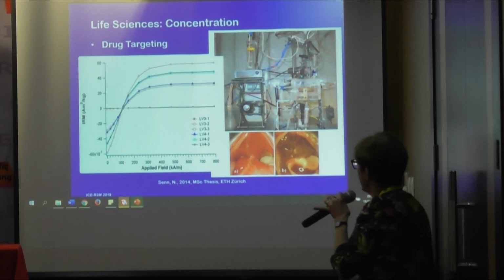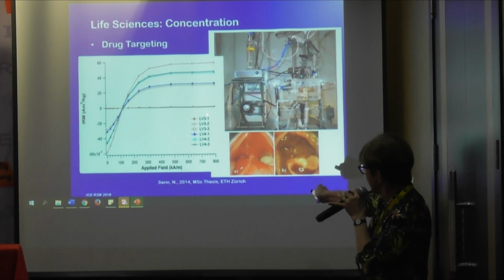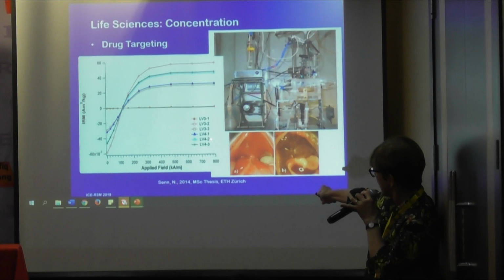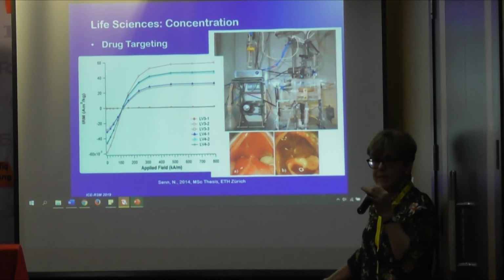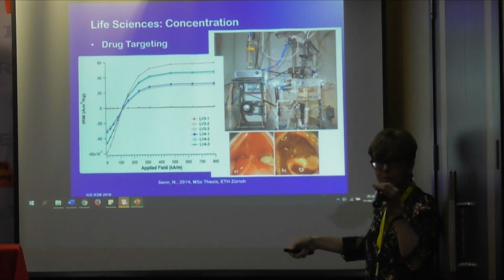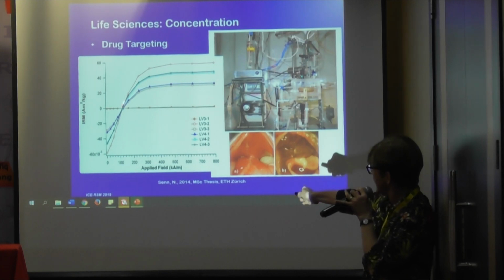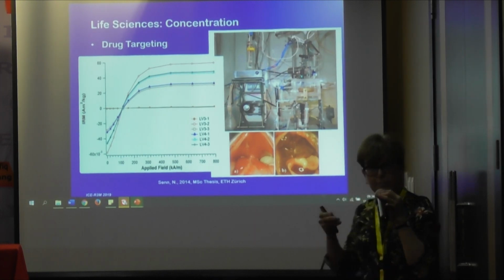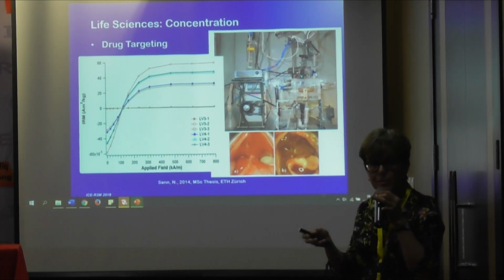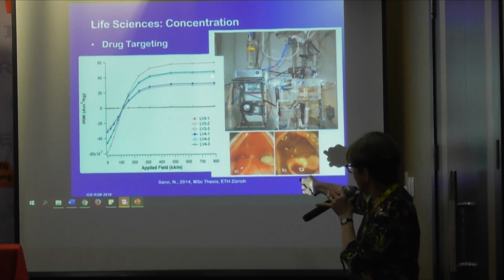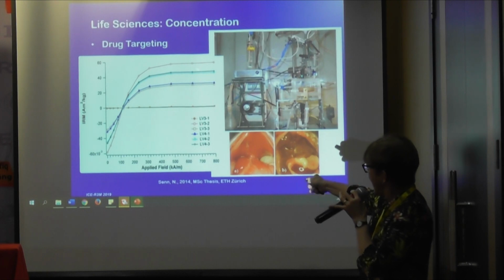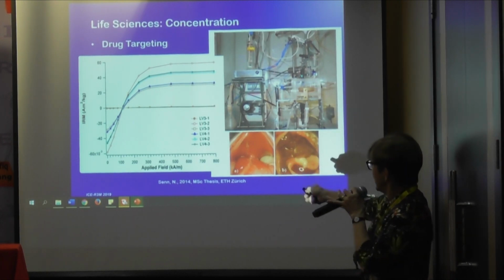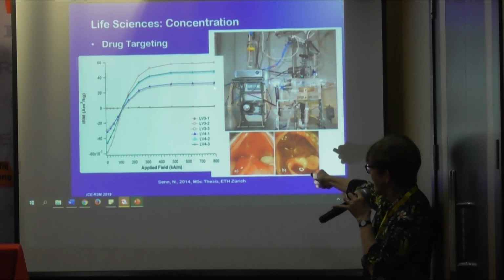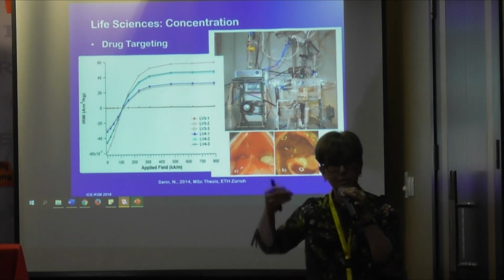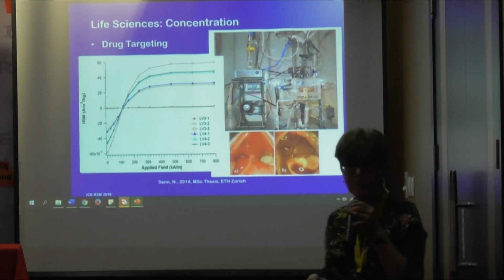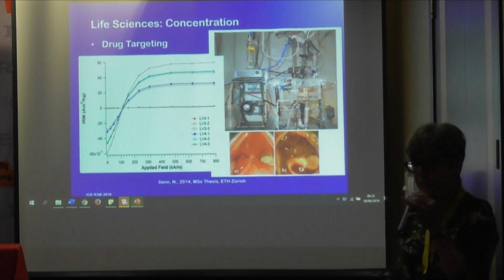Okay, next. Here you see some IRM acquisition curves for 2 of the livers. Liver 3, where we have lobe 1, 2, 3, and liver 4, lobe 1, 2, 3. In liver 4, they just put a magnet close to the liver, but not close to a particular area. You can see from the bluish curves that you get slightly different values, so the nanoparticles are not distributing homogeneously throughout the livers, but they are being delivered. In the case of liver 3, they actually tried to put the magnet close to one side of the liver, so you can see that 2 of the samples had a high IRM, and 1 sample had almost none. The one furthest from the magnet did not collect any particles. That was a good thing for them, for being able to target very accurately. Okay?